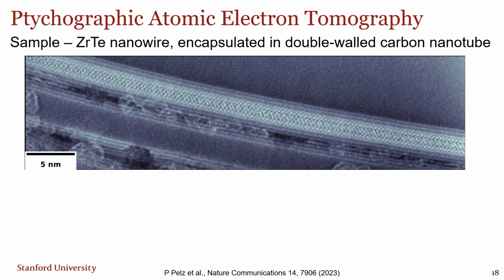This is an Alex Zettel sample. It's a double-wall carbon nanotube with a zirconium tellurium nanowire encapsulated inside. And their lab had formed many of these different structures using their chemistry techniques, but nobody knew the structure of any of the more complex nanowire nanotubes here.